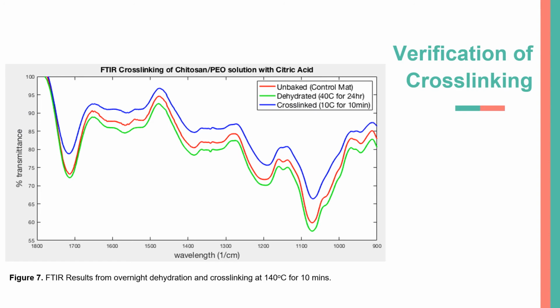FTIR results in literature predict that as dehydration occurs, the bonds break and the percent transmittance would decrease. As the material was then cross-linked and new bonds formed, the percent transmittance should increase. This can be seen as the percent transmittance decreases from the control shown in red to the dehydrated mat shown in green, and then increases as it is cross-linked from the green to the blue.